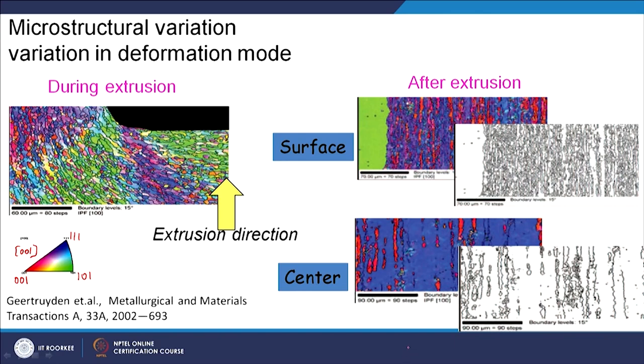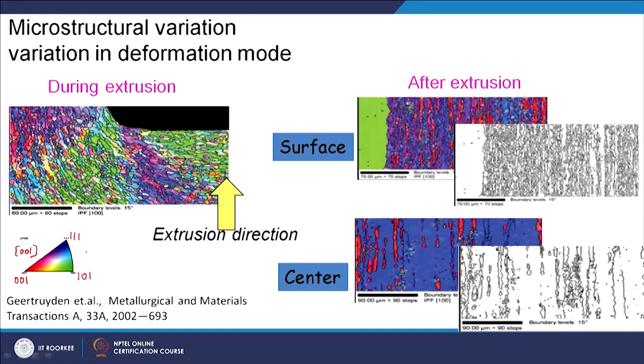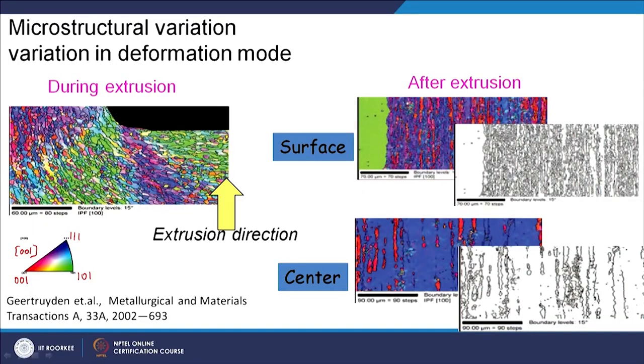So, basically what these colors are showing is given as a key here. If any grain is red in color, that means the 001 axis of that grain is coming out, from the surface here. If it is a green colored grain, that means the 110 axis is coming out. If it is blue, then it is basically the 111 axis coming out. So, you can see again very nicely how the orientation of the grain is changing during the deformation process.